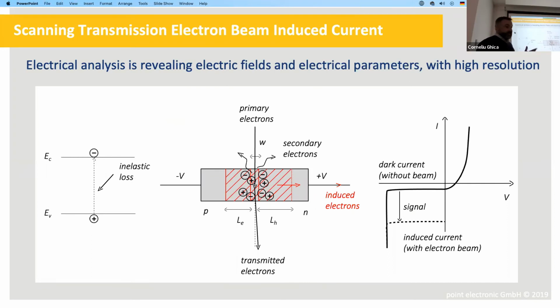Very similar, or the same principle, however, there's a major difference: the sample is always thin. So that means the primary electrons are going through, they're becoming transmitted electrons. So we don't really have an absorbed signal so much, but we still have emitted electrons, which in these techniques tend to be called, more recently, secondary electron beam induced currents. But we are also losing electrons from the sample, again, a function of thickness, a function of density.